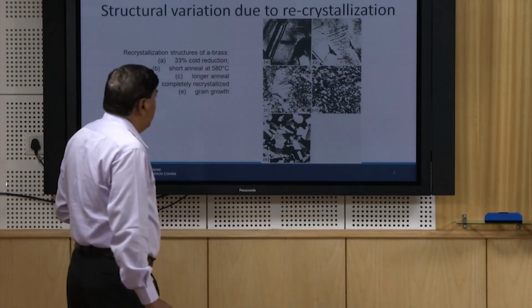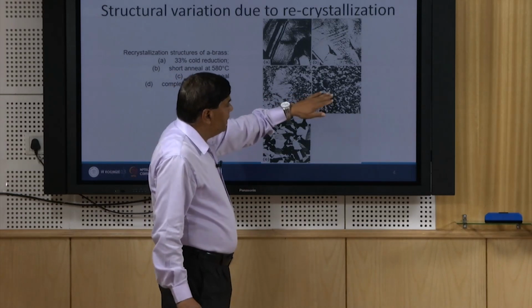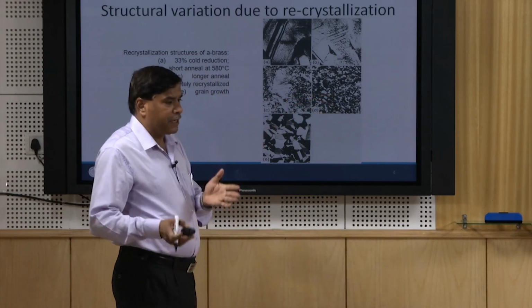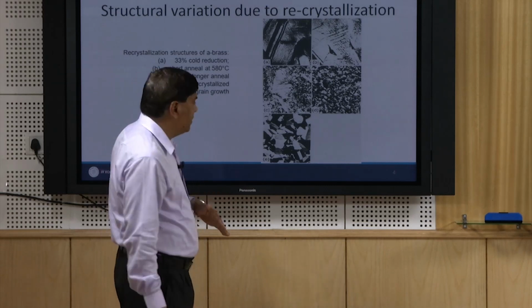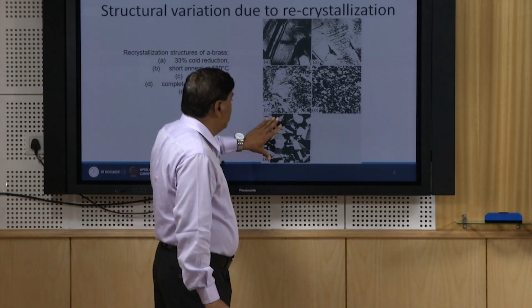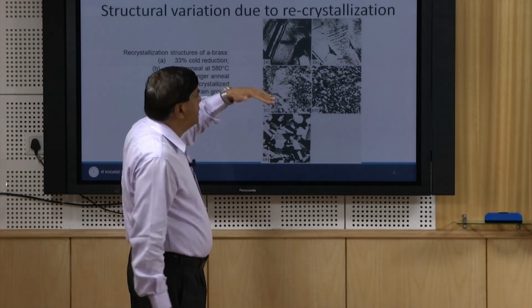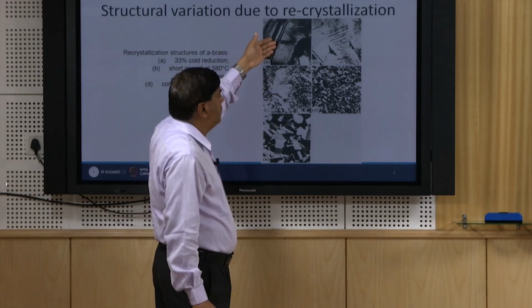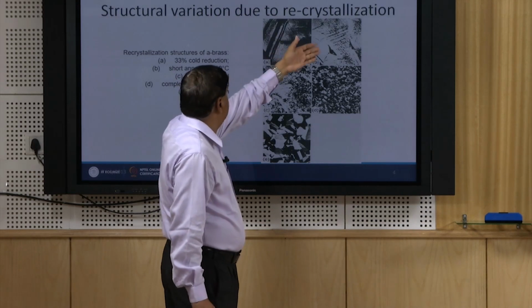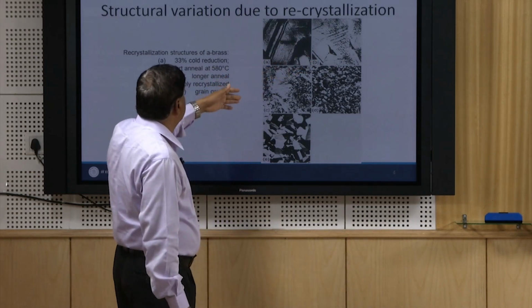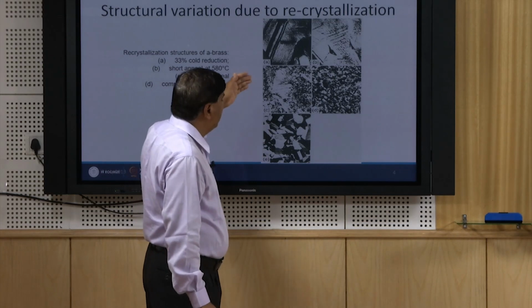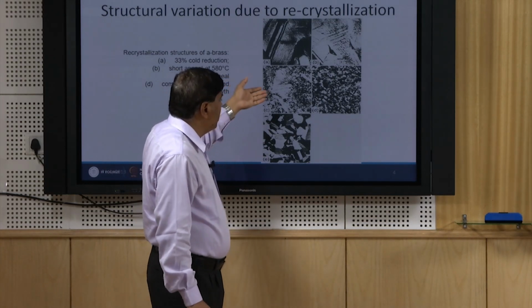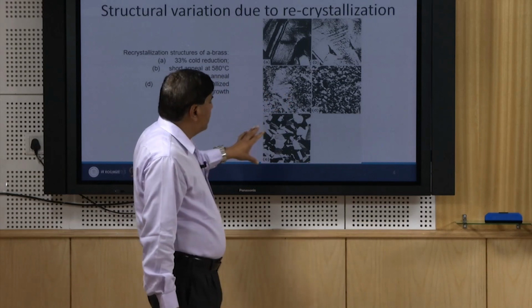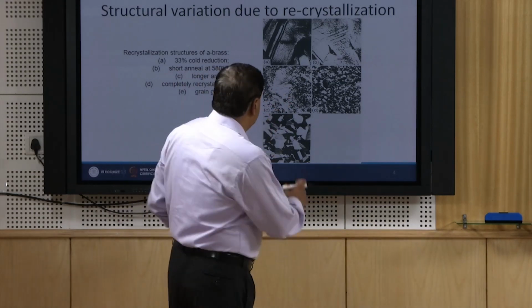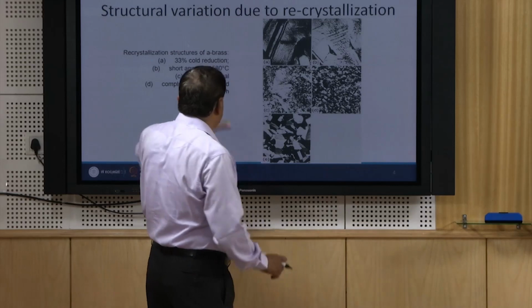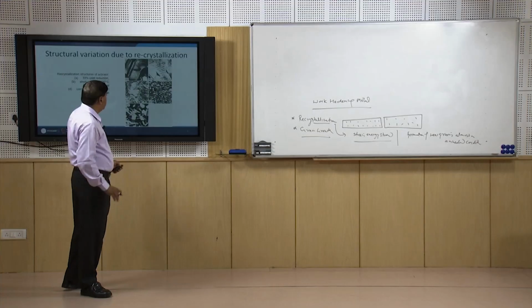that is called annealing. And if after the complete recrystallization, further exposure at a high temperature during the welding continues, then it results in the coarsening of the grains. So, the material right from its original condition in deformed state showing a large number of dislocations, and these dislocations will keep on decreasing with the increase in time at a particular temperature during the annealing, and overexposure causes the grain growth. So, this is the third or last stage. So, first the recrystallization and thereafter the grain growth takes place.